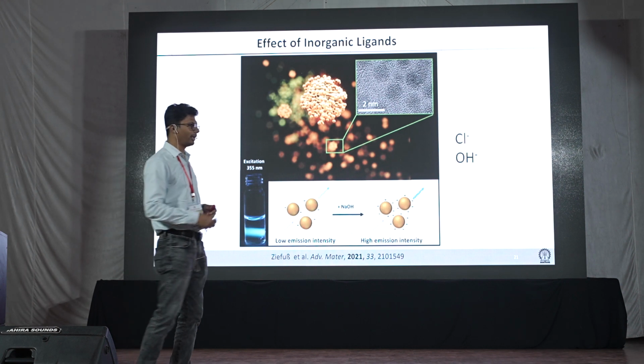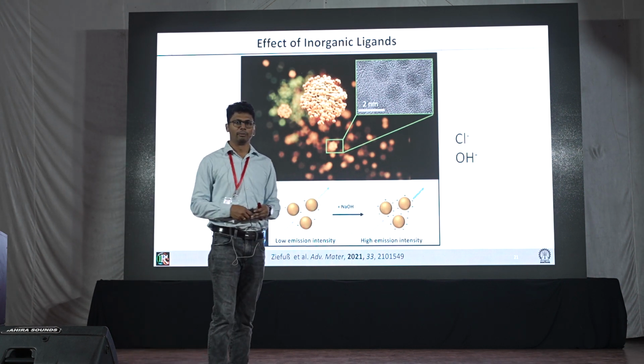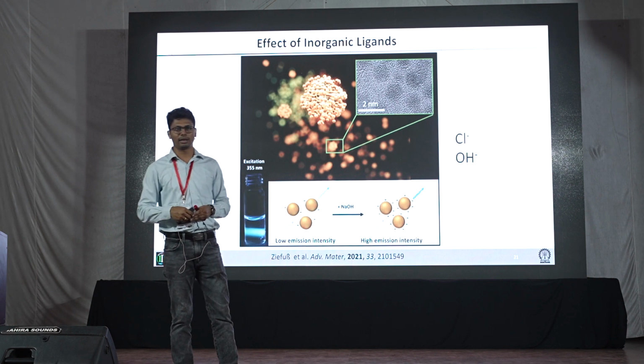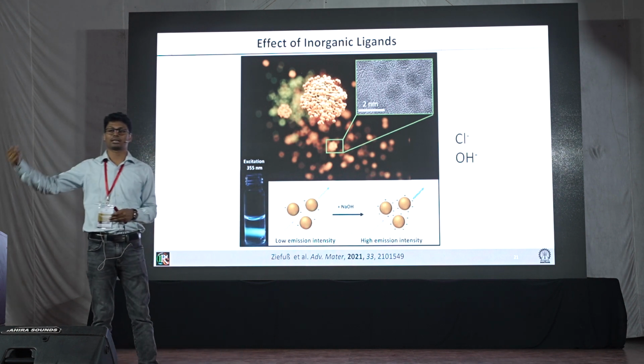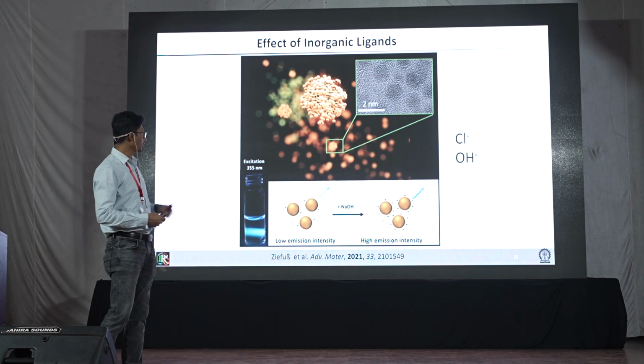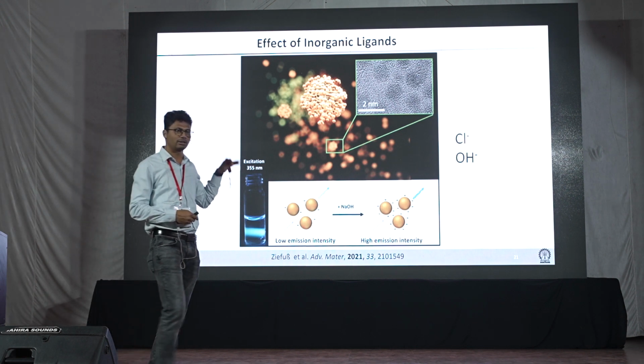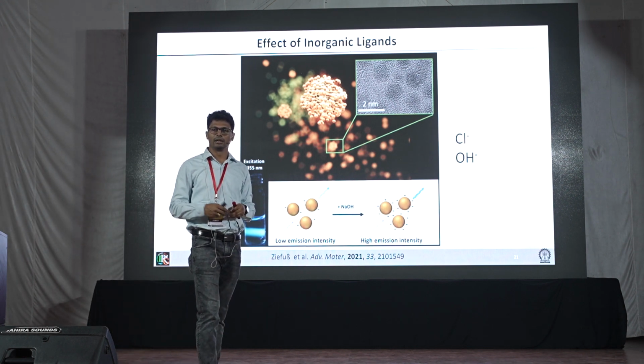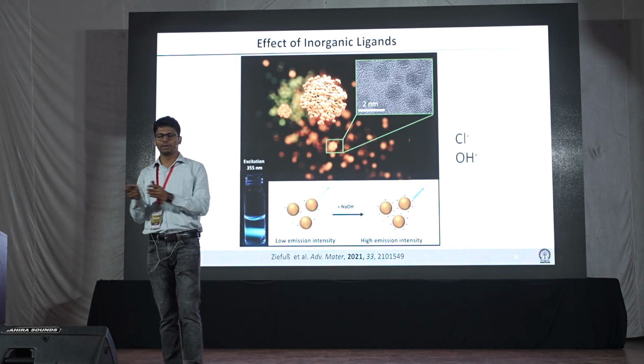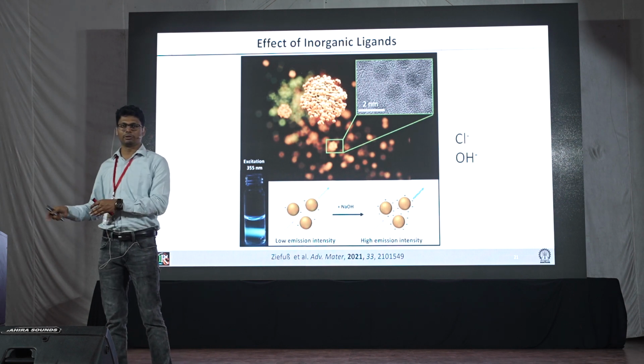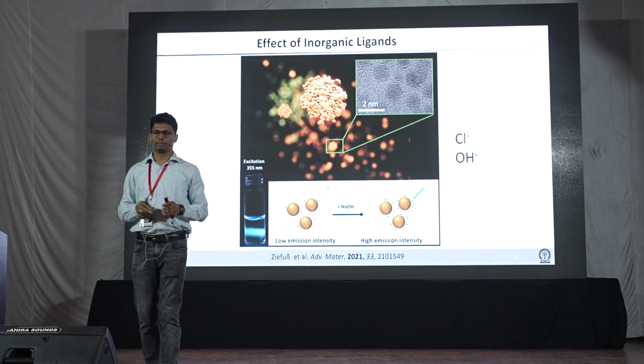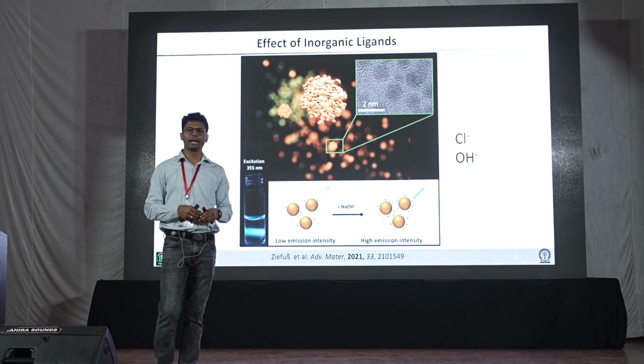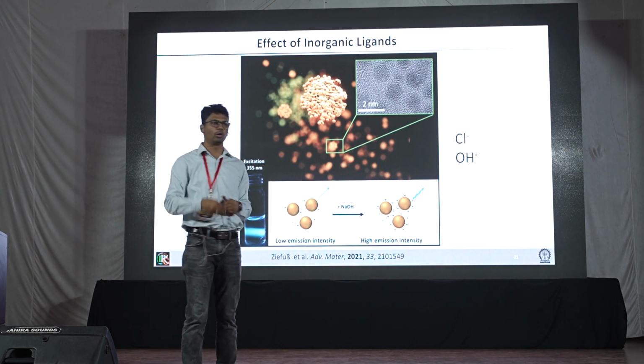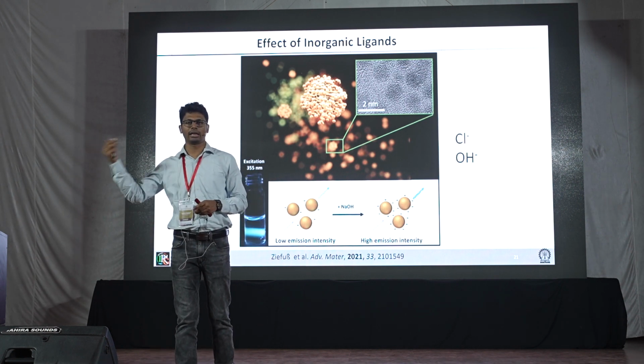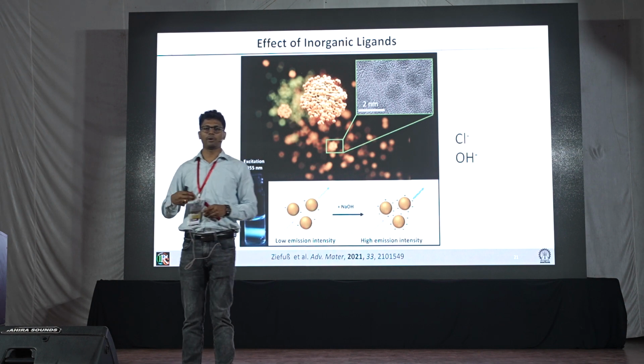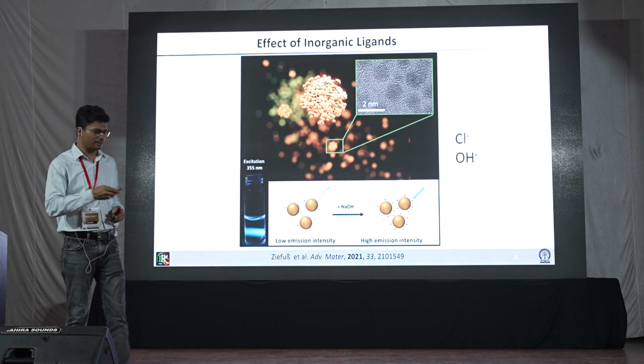People are debating now whether the kernel takes the major role in the luminescence, or the ligand to metal charge transfer is the leading part. Some of these experiments suggest that indeed the origin of luminescence might be towards the kernel, which is basically the metal core part, whereas ligands play an amplification role: they can promote, they can decrease, they can modify. That possibility is there from the ligand aspect.